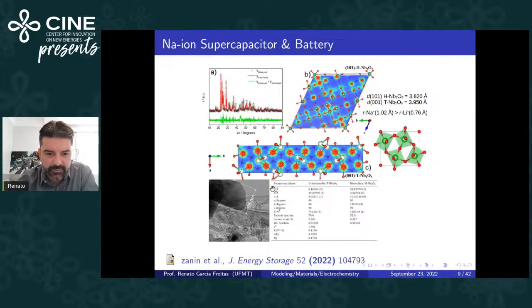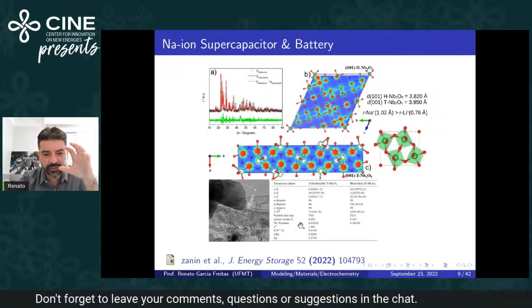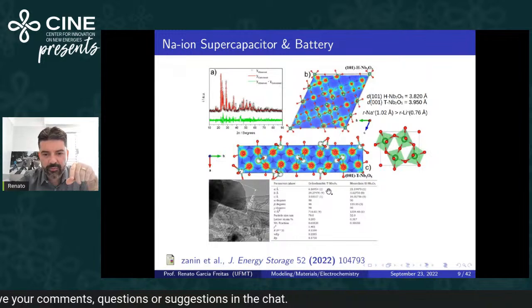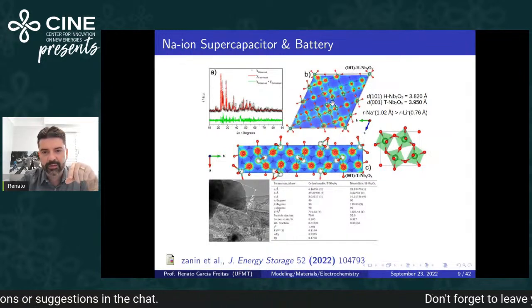And the crystallography parameters, as you see here, a, b, c lattice parameters, alpha, beta, gamma, and pay attention to this part, particle size. The particle size of 70 for the orthorhombic phase, orthorhombic niobium oxide, is larger, 70, compared to monoclinic, 52. The lattice strain for orthorhombic is lower, 0.2 compared with 0.31 for monoclinic. And we have a large fraction of this phase here. You see the fraction of 0.61 for orthorhombic and 0.38 for monoclinic.